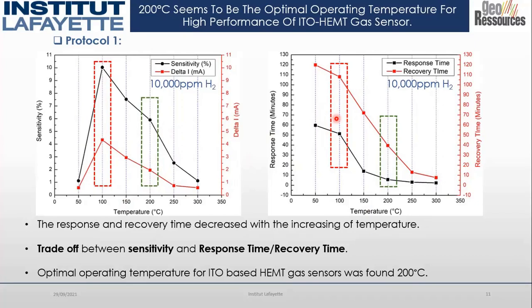By analyzing the two curves, we chose the suitable operating temperature of 200 for our application. You may wonder why we chose 200 instead of 100, where the sensitivity is very high, close to 10%. There is a trade-off between sensitivity and response and recovery time. If we choose the highest sensitivity, the response and recovery time is so high that the sensor is declared a slow sensor. So for our application, we had a reasonable sensitivity, response time, and recovery time at 200 degrees. So we chose 200 degrees as the optimal temperature.